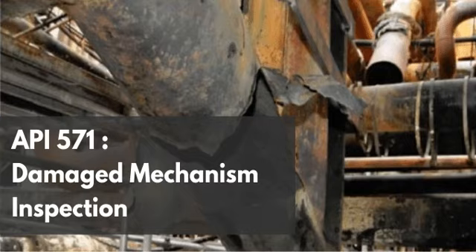Exactly. But the specific local chemistry of alkaline carbonate water combined with H2S creates a highly aggressive localized environment. The thermodynamics shift completely. So the fluid just constantly attacks those films. Yeah, it continuously strips away those iron-based films. If the steel is trying to protect itself by forming these iron carbonate or iron sulfide films, what exactly is stripping that armor away faster than it can heal? It's essentially a repassivation kinetics issue. The steel is trying its hardest to heal itself by precipitating a new iron sulfide or iron carbonate scale. But the local environment is just dissolving that scale faster than it can form.